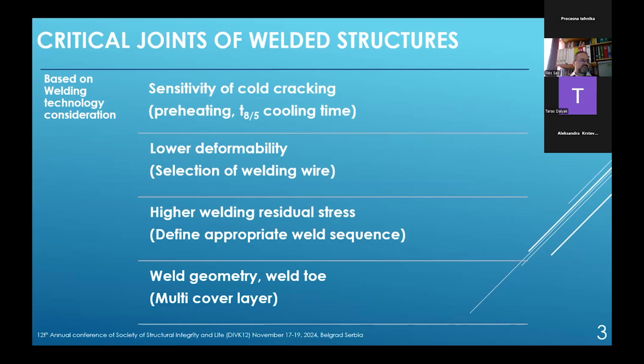First of all, if we consider the criticality and why the welding of high-strength steels is critical, we have to use two approaches. The first approach is the manufacturing point of view. In manufacturing, the first and main issue is that high-strength steel materials are really sensitive to cold cracking. Therefore, a really narrow gap is required to keep the t8/5 time, in some literature, between 5 and 10 seconds or 5 and 12 seconds. It gives a really narrow area from a welding point of view.